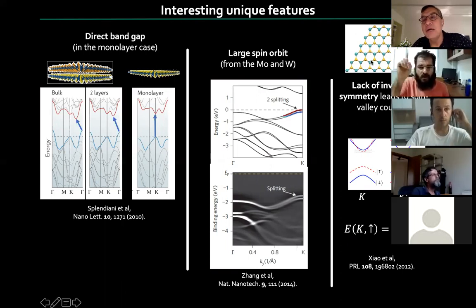So if you look at this image up here, you can see that it is not inversion symmetric. If you were to flip the crystal, you see this bond between green and yellow will be in a different orientation. And that means that you broke inversion symmetry, and together with the spin gives rise to this locking of the valley and the spin.